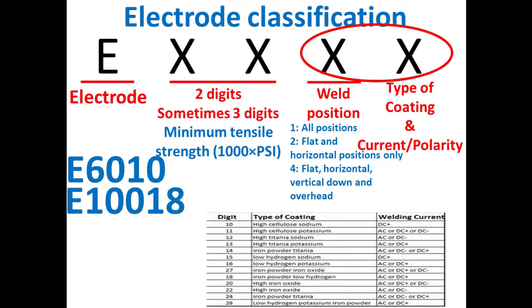Another example, E10018. E means that this is an electrode used in arc welding. 100 means that the minimum tensile strength of this electrode is in the order of 100,000 psi. 1 means that this electrode can be used in all welding positions. And 18 means that the type of the coating is the iron powder low hydrogen, as it is indicated by the table, and the welding current is AC or DC plus. AC means alternating current, and DC plus means direct current with reverse polarity.